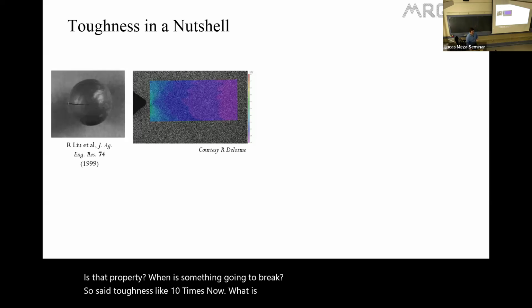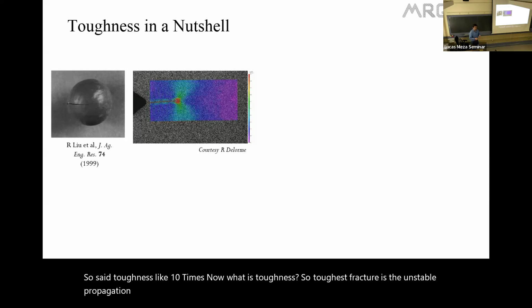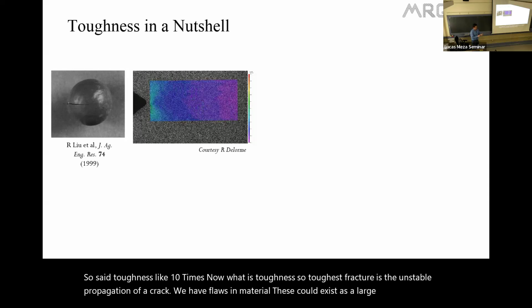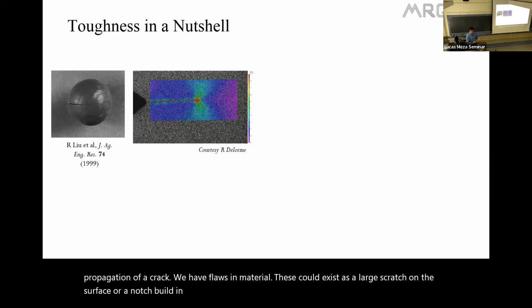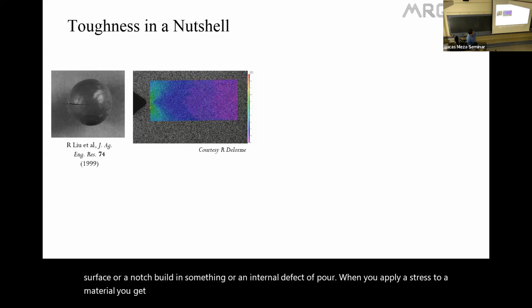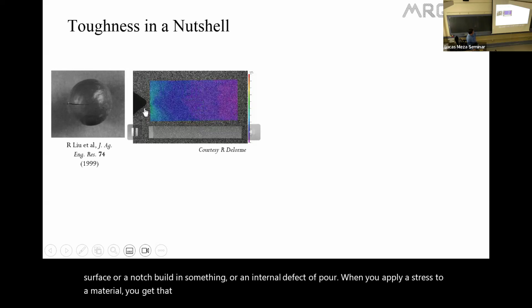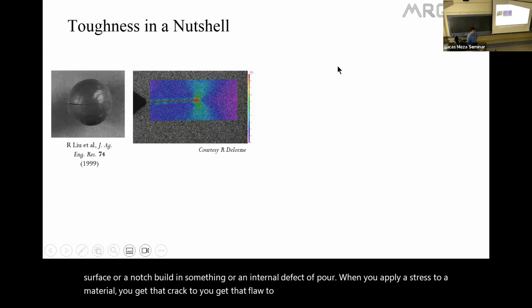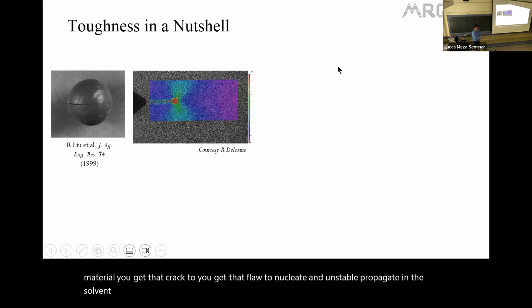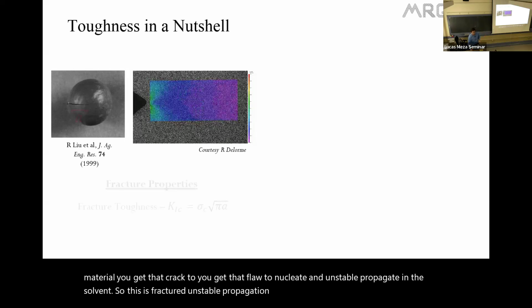What is toughness? So toughness, fracture, is the unstable propagation of a crack. We have flaws in material. These could exist as a large scratch on the surface or a notch milled into something, or an internal defect, a pore. When you apply a stress to a material, you get that flaw to nucleate and unstably propagate in the solid. So this is fracture, unstable propagation of flaws.